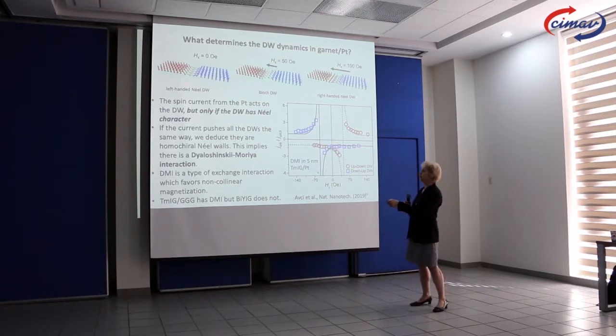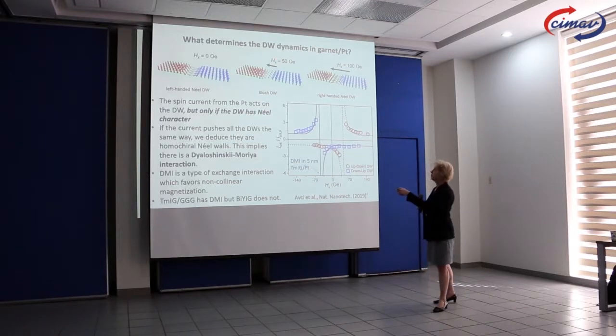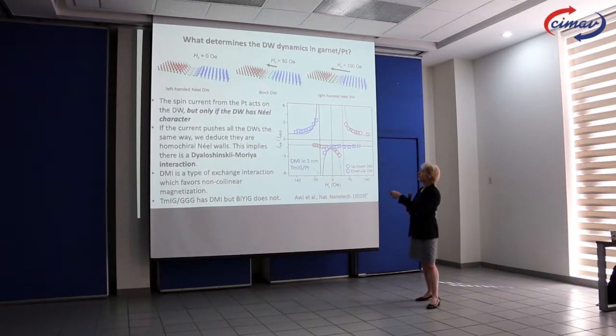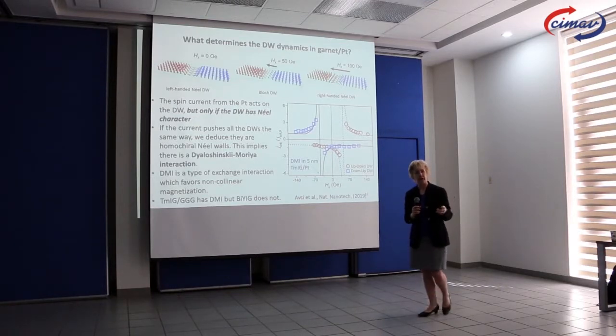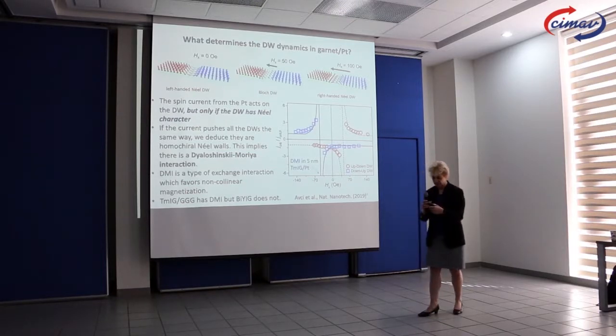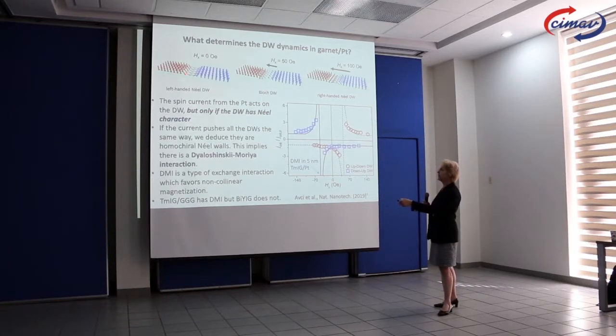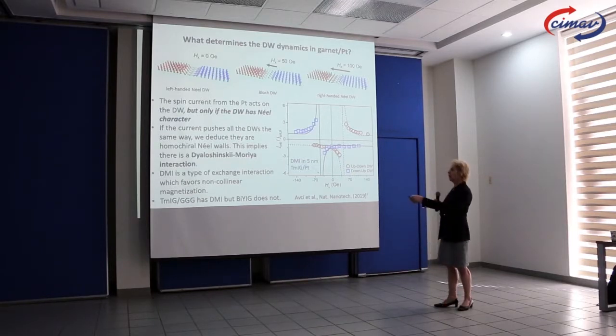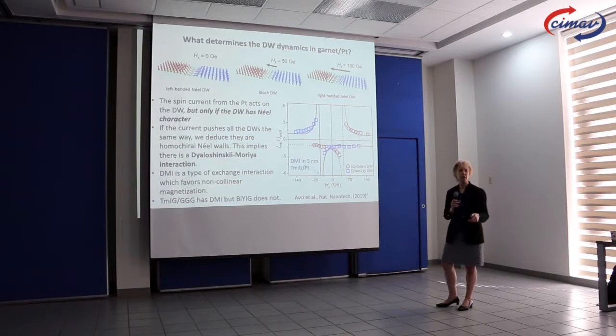So what this tells us is that the thulium garnet has this kind of domain wall, but the bismuth garnet has this kind of domain wall. So why should that be? Well, this is the expected kind of domain wall, and this one is not. And the reason this one is present is because of an interaction called the Dzyaloshinskii-Moriya interaction, or DMI, which is a kind of exchange interaction that favours non-collinear magnetism. So normally we think of exchange as making things parallel, or anti-parallel if it's negative, but the DMI makes them have a particular angle with respect to their neighbours. And so it favours a kind of chirality in the domain wall. They're either all left-handed or all right-handed, but you don't get a mixture of them.